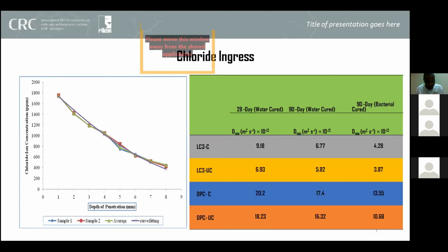One of the error fitting curves obtained is shown in the graph here. The apparent diffusion coefficients obtained from different samples are shown in the table. At 28 days of curing, the limestone calcined clay which was cracked showed higher apparent diffusion coefficient, while the uncracked one showed lower chloride diffusion.